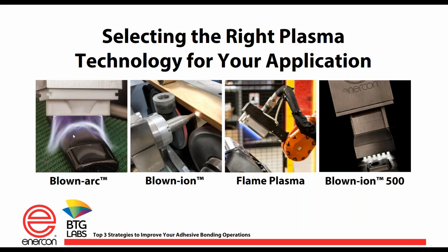It's a little bit slower treatment. We're talking 5 to 15 feet per minute, depending on your application. And it can only be used on non-conductive surfaces. So if you've got a conductive surface like a metal, you can't use a blown arc on that. But if you do have a non-conductive surface, you can treat up to 7 inches wide very easily. It's great for printing. It's great for labeling, just increasing the surface energy of a larger area.